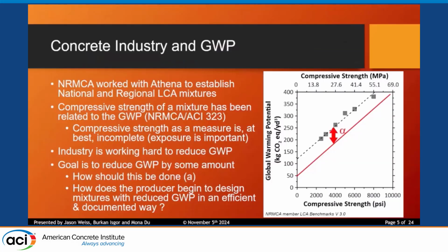So to start with, part of this big push is using the data that NRMCA generated through their Athena program to establish what's going on right now in terms of the total GWP of mixtures throughout the US versus the compressive strength. If you take that document and plot the data that's in the tables, you will notice a trend that the global warming potential increases as a function of compressive strength. Now, what ACI 323 is encouraging us all to do is to move from this line down to the red line by some value alpha, right?